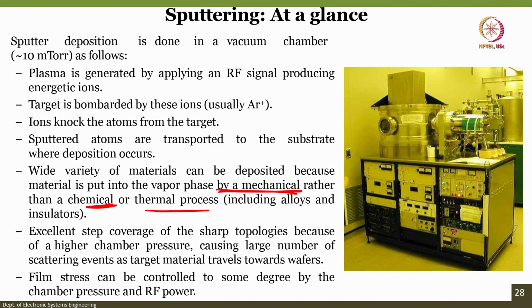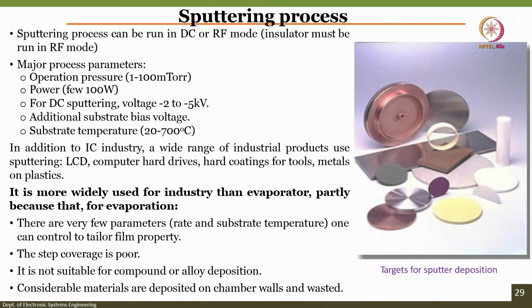Excellent step coverage is an advantage on sharp topologies because a higher chamber pressure causes a larger number of scattering events. Film stress can be controlled to some degree by chamber pressure and RF power, right? So stress can also be controlled using these parameters. If you want to see the sputtering process at a glance, it can be run in DC or RF mode. The insulator must be run in RF mode, it's important.